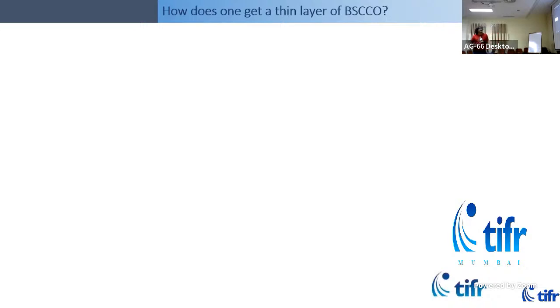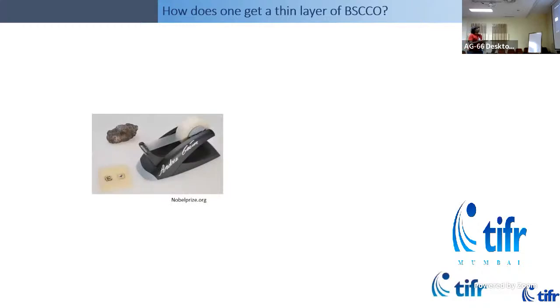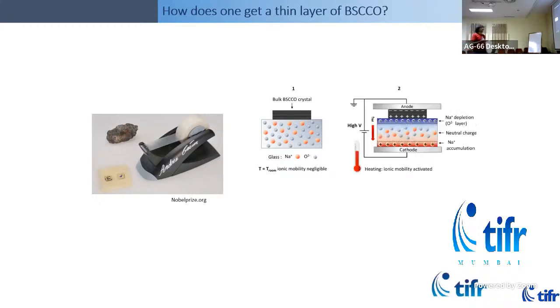So the way one makes these superconducting layers, these are single crystals because they're taken from bulk crystals. For most of the graphene work and other 2D materials, we can use the technique of peeling off with tape. It doesn't work with this material. So we use for this work a technique called anodic bonding, which is essentially known in the semiconductor industry for many years.